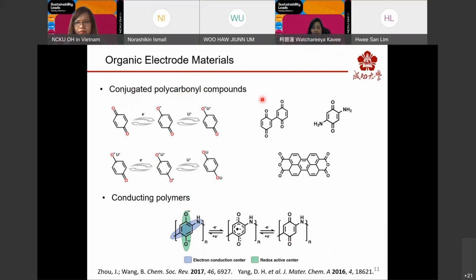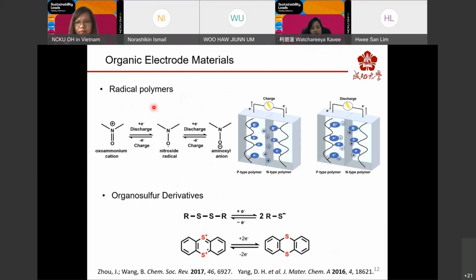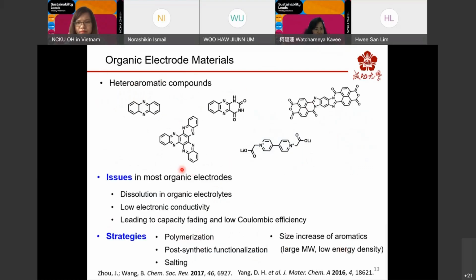conjugated polycarbonyl compounds, conducting polymers, radical polymers, organosulfur derivatives, and heteroaromatic compounds. However, in most organic electrodes, issues such as the low electronic conductivity and material dissolution in the typical organic electrolyte generally lead to capacity fading and low Coulombic efficiency. Several strategies have been used, such as polymerization and post-synthetic functionalization and salting. However, this strategy may result in an increase in the molecular weight as well as low energy density.